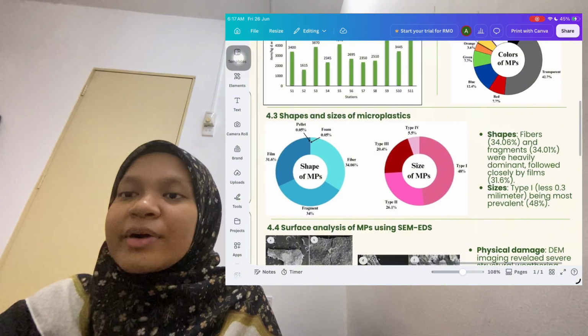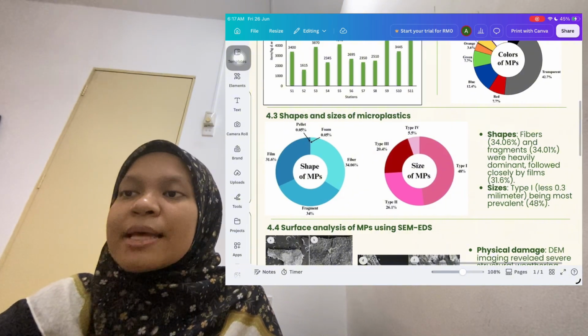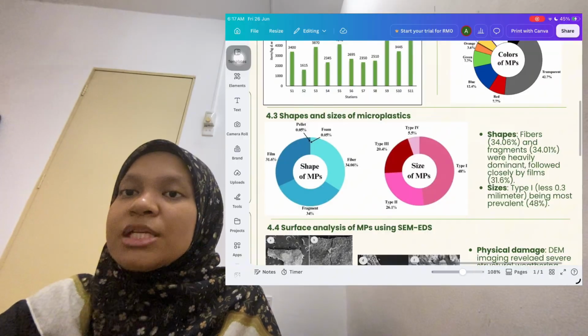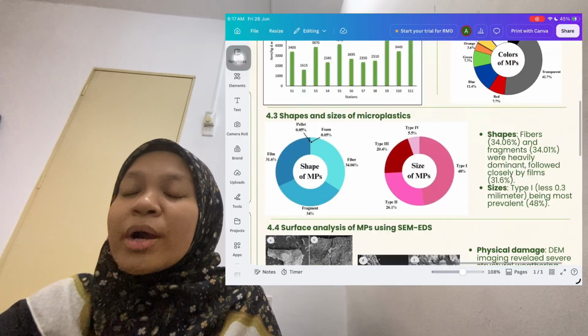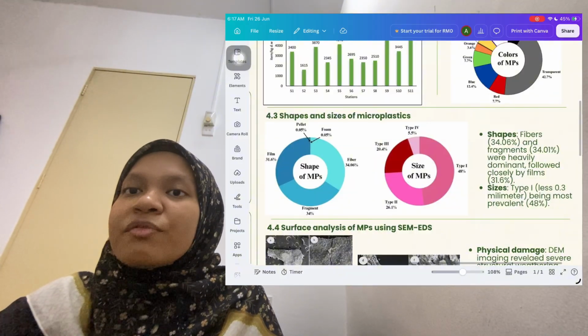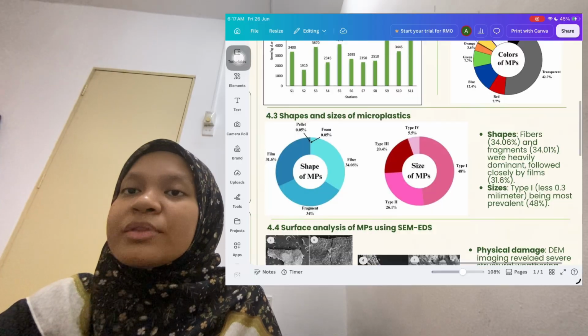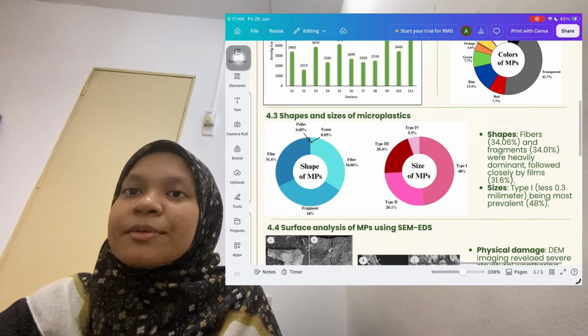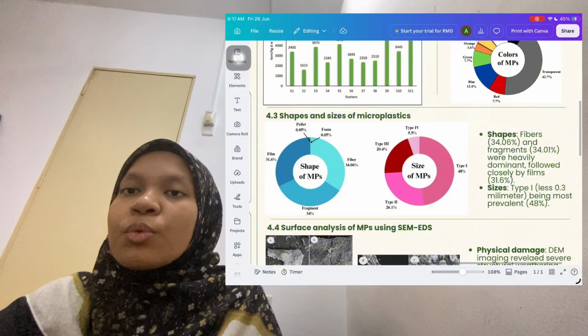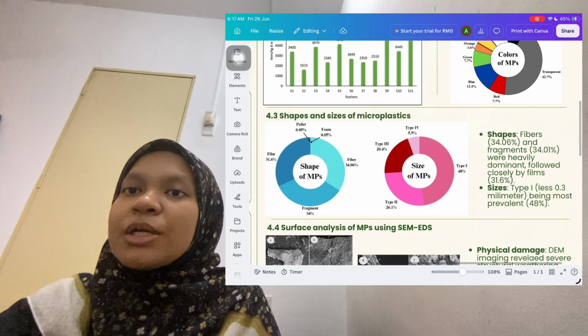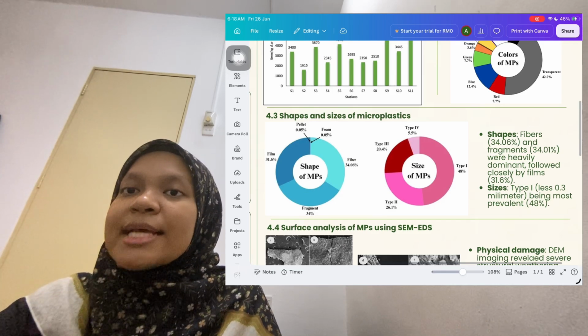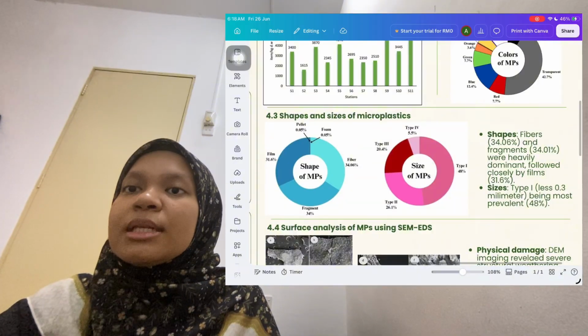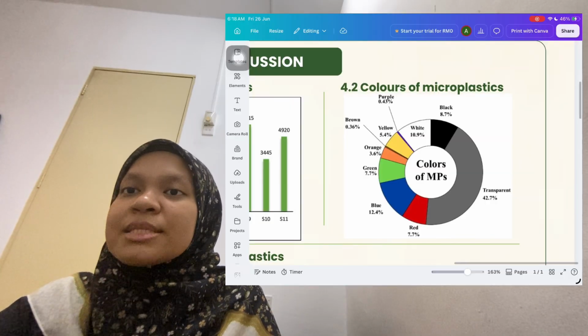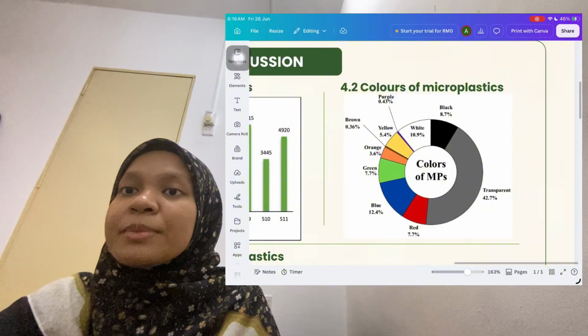When looking at their physical profiles, fibers and fragments heavily dominated the samples, accounting for roughly 34% each, followed closely by films at 31.6%. The immense presence of microfibers correlates directly with the large amount of discarded clothing observed at the site. In terms of sizing, type 1 particles, which are smaller than 0.3 mm, predominated at 48%, showing that extensive environmental weathering is constantly reducing these plastics into highly minute fractions.